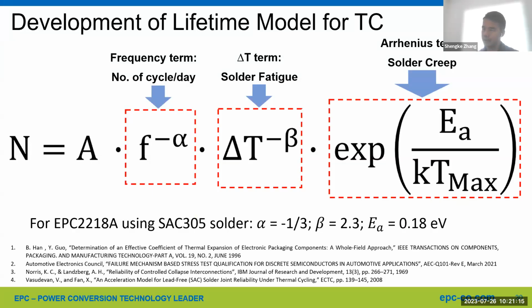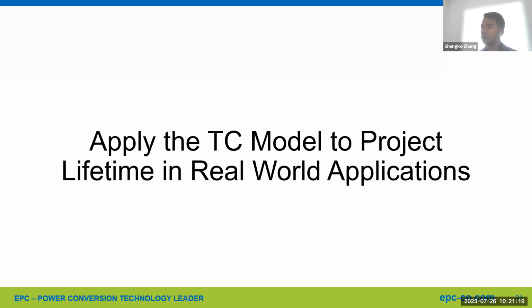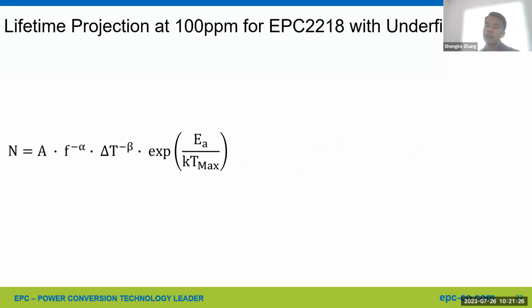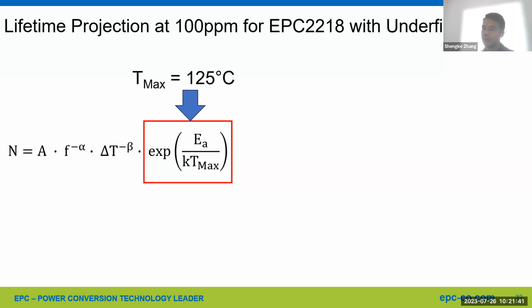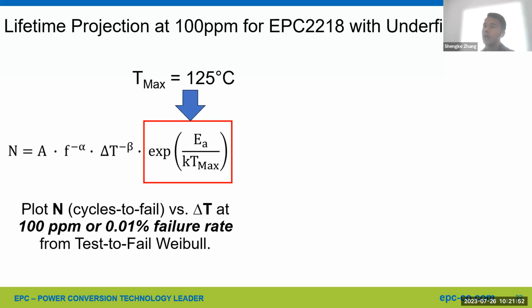Okay, the next question: so we have this lifetime model. How do we use it? And how can we apply the model to project lifetime in a real world application? So let's first start with this Norris-Landzberg equation, the TC lifetime model, again. First, let's assume the Tmax is 125C, possibly the worst case scenario in application. Therefore, the Arrhenius term essentially is a constant, a coefficient. We can lump it into a coefficient. Now we can plot the N on the left side of the equation, cycles to failure, as a function of delta T at 100 ppm or 0.01% failure rate. We collected this from the test to fail Weibull plot.